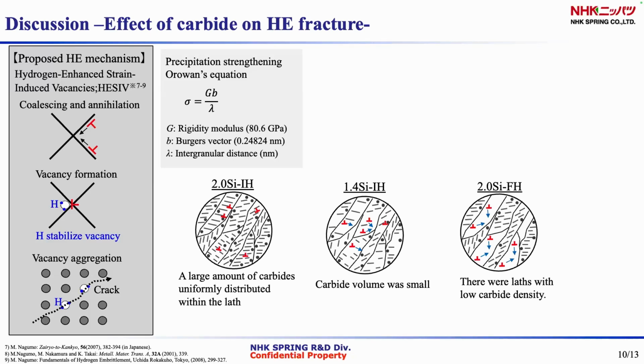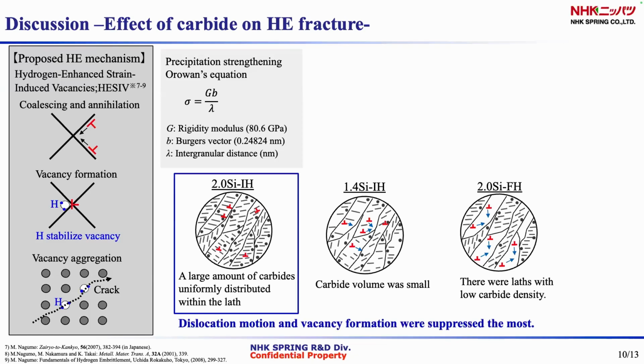This figure shows the distribution of carbides over each specimen. 2.0Si-IH steel still has a large amount of carbides, uniformly distributed within the grains. In contrast, the 1.4 silicon steel's carbide volume was small, and 2.0Si-FH steel has many laths with low carbide density. Therefore, we expected that in 2.0Si-IH steel, dislocation motion and vacancy formation were suppressed the most.